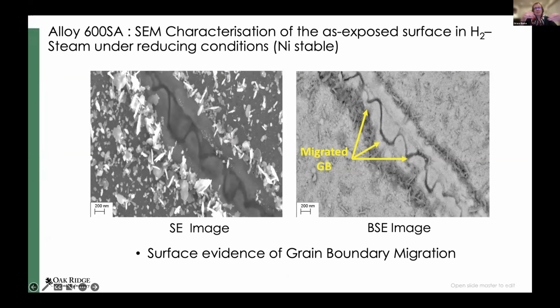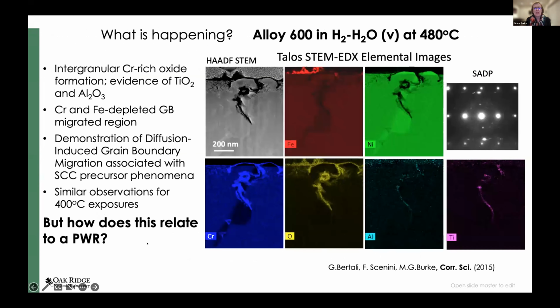Can we get a better idea globally without doing a huge number of FIB cross sections? And of course, you can, by very careful secondary and backscattered electron imaging on the as-oxidized surfaces, or the as-reacted surfaces. And you can see those squiggles on the grain boundary, where it has migrated.